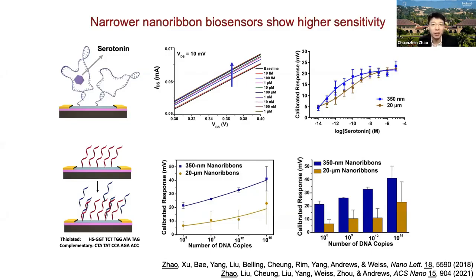It is suggested that the surface-to-volume ratio is critical for the sensitivity of biosensors. For the same thickness, narrow nanoribbons have higher surface-to-volume ratios, thus leading to a higher sensitivity. We investigated the sensitivity at different pH, aptamer sensing, and also DNA sequencing. The results showed that transistors with 350 nanometer wide nanoribbons have higher sensitivity than the 20 micrometer wide ribbons, which confirmed our hypothesis that devices with higher surface-to-volume ratio have higher sensitivity.